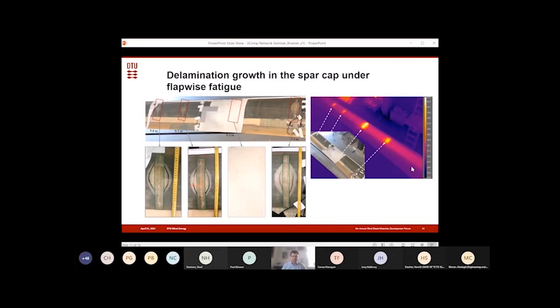But the interesting part is that you clearly see all 4 defects with a thermal camera. And actually, it turned out that the one under the paint was the most critical. It was the one that grew more and actually caused the blade to fail. And it's also seen that it heats up more. I mean, there's more thermal energy coming from this wrinkle.